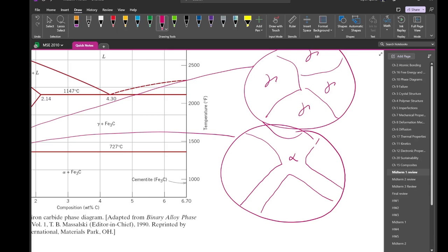If you have to form another phase, you have choices. You can either form it in the middle of the old phase as a precipitate, and that means a really high surface area, because every one of those little tiny particles has a surface area around it. Surface area, think surface energy. That's a penalty. Or you can put it on the grain boundary, which already had a surface, right? So you're replacing an old energy surface that cost you something in terms of energy with a new one. So that's where it's going to prefer to go if it's a high enough temperature.